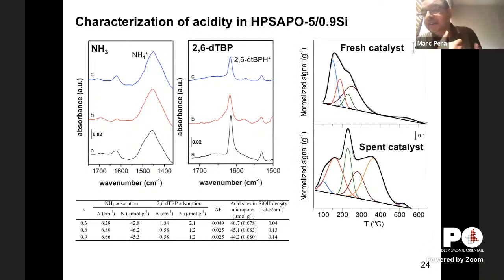And we could also characterize in more detail these sites by ammonia TPD. Here I'm just comparing the fresh and the spent catalyst. So most of our catalysts are medium strength, and what we call intermediate strength, here located by this descriptor. We have a big band in the beginning that is weaker sites. What is very interesting is that along the reaction, we have a new band that appears. And that points out that somehow we have some hydroxylation of the sample, probably outside the particles in the mesopore domain.